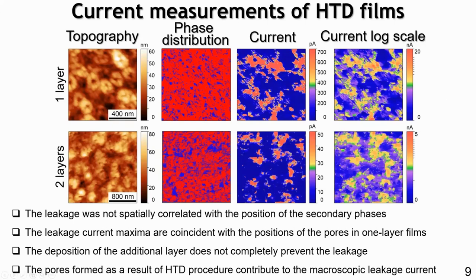And even if we put another layer on the top, so this is one layer, and we put another layer on the top, there are still some current spikes, and especially they're seen on the logarithmic scale. We have this large increase of the current which is connected with the position of the pores, but we also have another contrast which is not so visible, and this contrast does not correspond to the position of the pores on the second layer. It means that we measure the current which goes through the pores on the first layer film. It means that the whole film is not uniform, so we have more or less conductive channels inside the film, and these channels